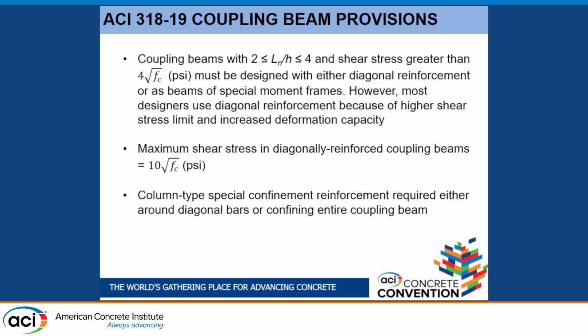If you're dealing with a diagonally reinforced concrete beam, you can design for a shear stress of 10 root of f prime c in PSI. You get 8 root of f prime c if you're dealing with special moment frame beams. Most designers choose the diagonally reinforced concrete coupling beam because of the higher shear stress, and it also exhibits much better behavior in terms of deformation capacity than a special moment frame beam.